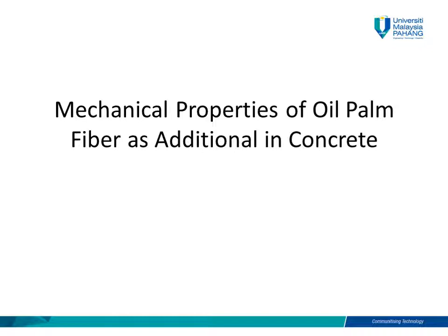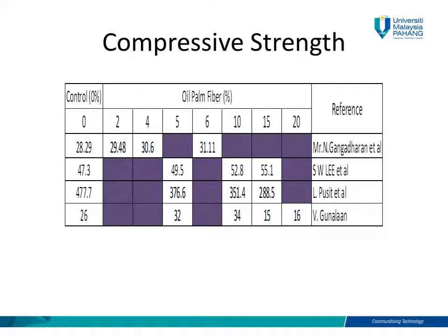Next is the mechanical properties of oil palm fiber as an additive in concrete. Okay, now is the compressive strength of the oil palm fiber by the previous researcher. The first one is Mr. N. Gangadharan. He has 3 replacements, and his replacements show an increasing trend, which is 29.48 to 31.11, higher than the control one. Second is S.W. Lee, who has 3 replacements, and his replacements show also an increasing trend line from 49.5 to 55.1, higher than the control one, 47.3.